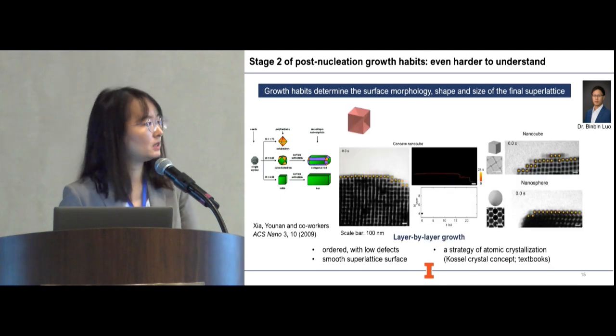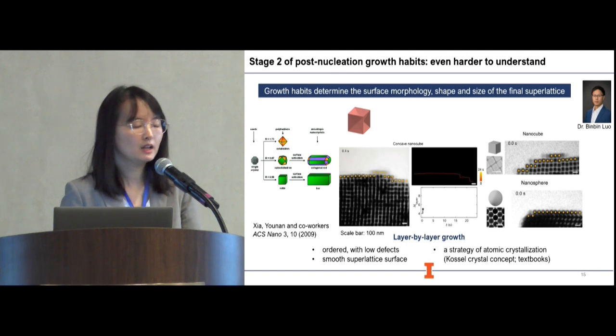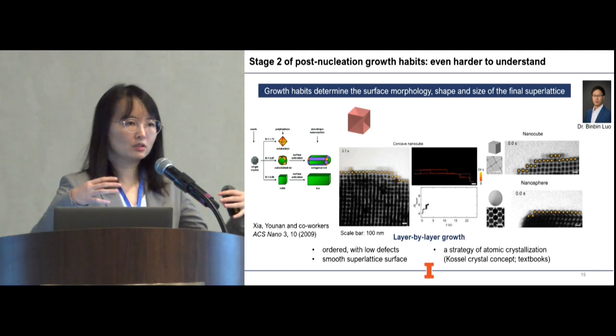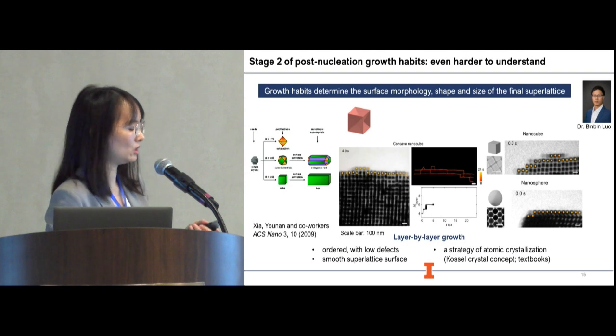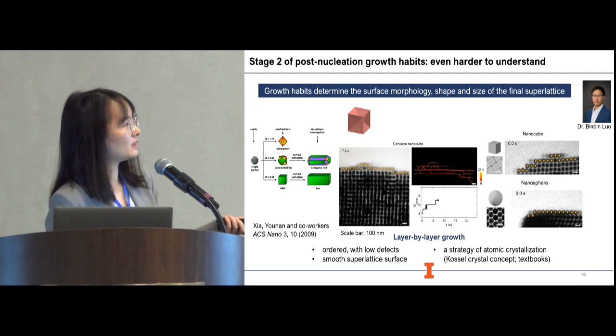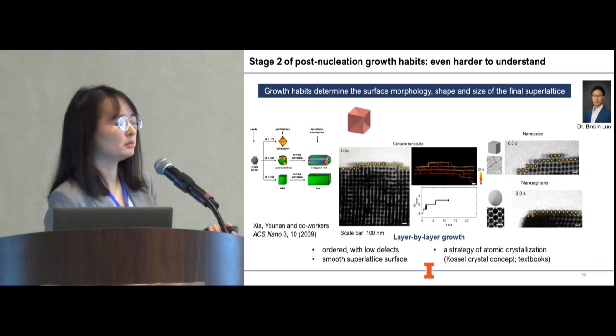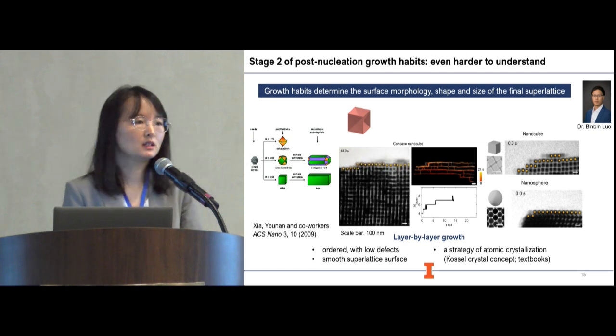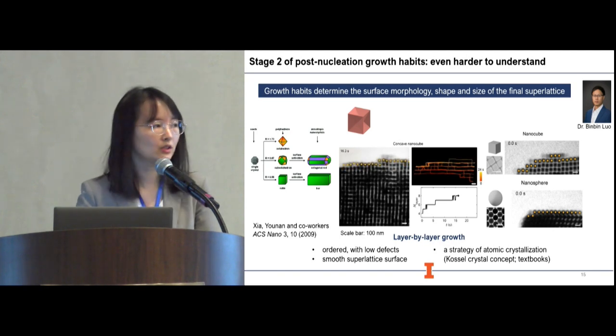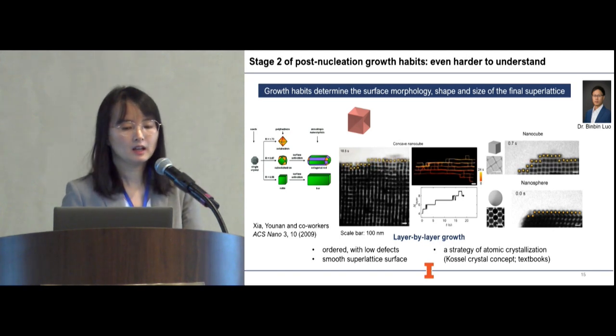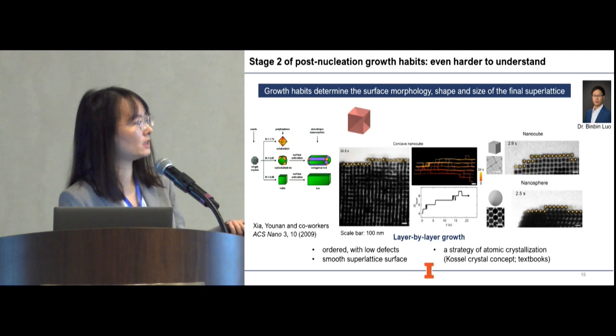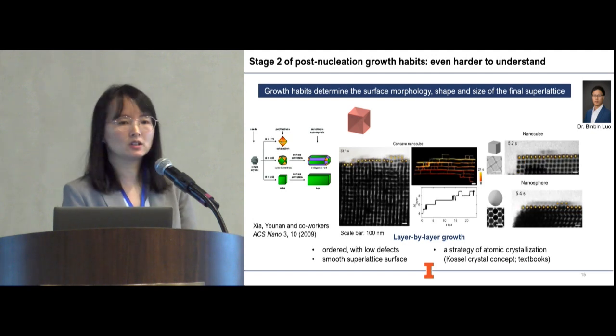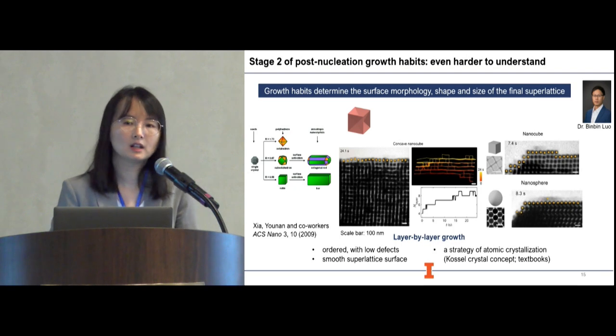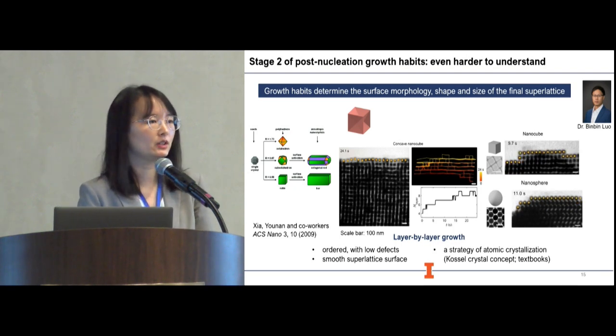And my student Bingbing was able to subsequently upgrade our liquid phase TEM procedure. So now we can actually watch the growth of a large crystal in 3 dimensions. So in this liquid phase TEM movie, you can see the incoming particles will form into one layer before they grow another layer. So this is a so-called layer by layer growth to ensure a flat surface. And then if you look at the other two particle shapes, although the interaction, the lattice symmetry is very different, they also follow the same layer by layer growth.